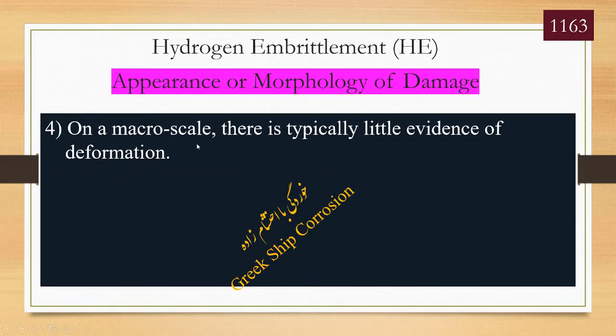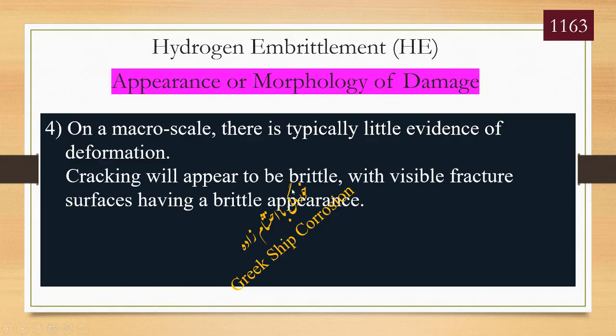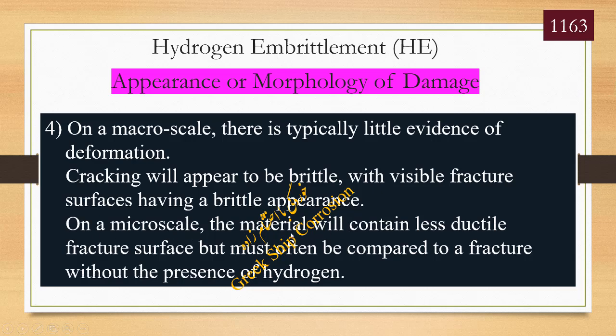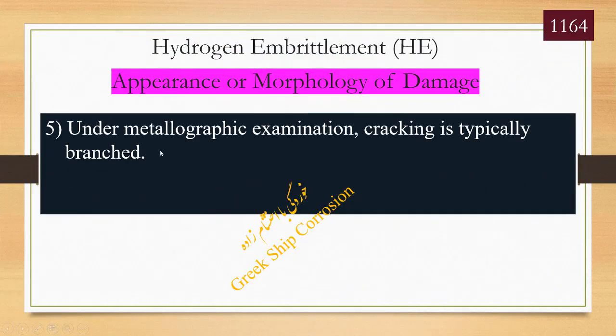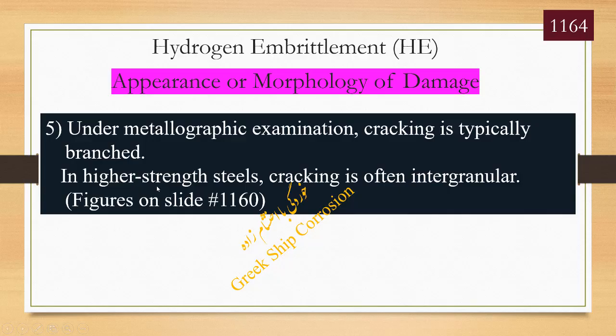4. On a macro scale, there is typically little evidence of deformation. Cracking will appear to be brittle, with visible fracture surfaces having a brittle appearance. On a micro scale, the material will contain less ductile fracture surface but must often be compared to a fracture without the presence of hydrogen. 5. Under metallographic examination, cracking is typically branched. In higher strength steels, cracking is often intergranular. Figures on slide number 1160.